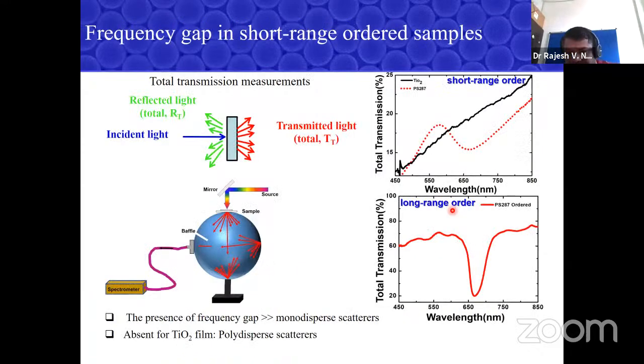And then we did a measurement, we passed the light. But when you characterize a disordered sample, it is not the linear transmission that matters. When I say linear transmission, you have the light which is coming directly to you. But in a disordered medium, the light gets scrambled, the light is randomized. So it propagates in all directions. So you send the light, it propagates in all random directions. So we need to collect what is called the total transmission of light, which not only accounts for the straight path, but also accounts for the other angle scattering.